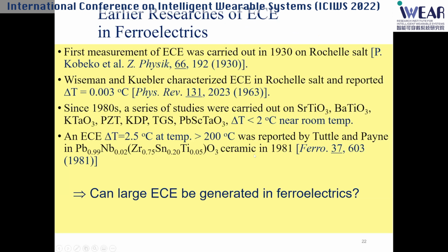We are not the first ones to study EC. The first report of electrocaloric study was in 1930, so it's nearly a century now. In the ensuing years, people found that at room temperature you can get an adiabatic temperature change of less than about 2 Kelvin, and at high temperature about 2.5 Kelvin — all in ceramics.